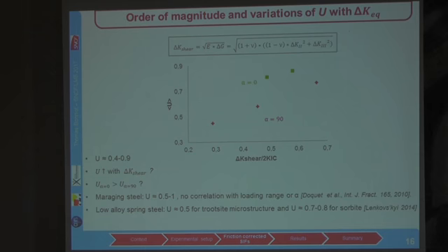And this u ratio is larger for alpha equals 0, which is consistent with the value of the induced opening from before, because we have more opening for alpha equals 90 than for alpha equals 0. And the range of u is consistent with the literature. And now that we have evaluated the friction effect, we can finally get the kinetics and growth rates.